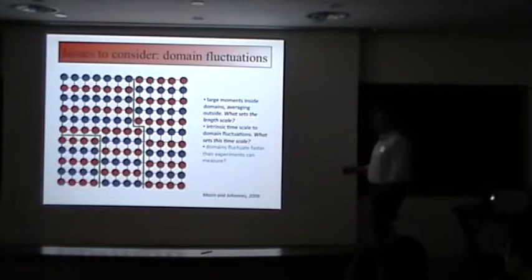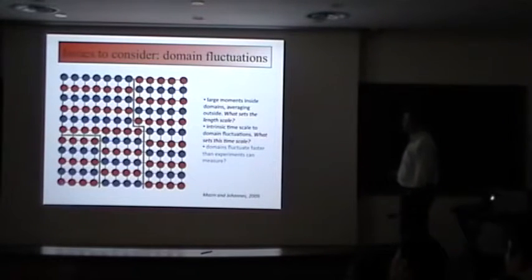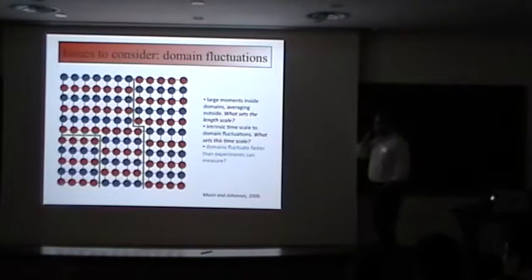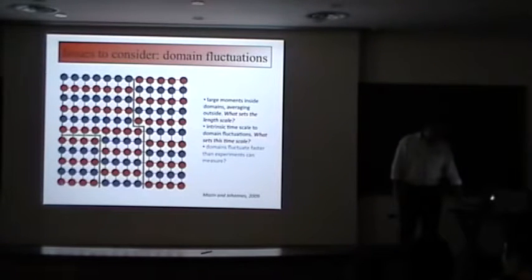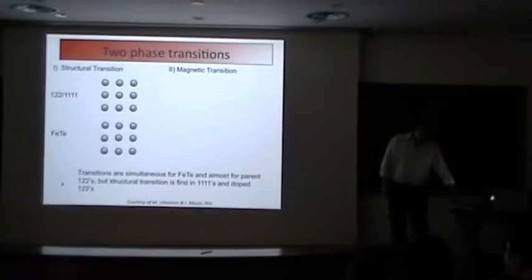So this is a way in which you could reconcile LDA and inhomogeneity of giving smaller moments, but it raises a number of questions: what sets the length scale of these domains, what are the dynamics of the domain walls themselves and how do they fluctuate, is there a time scale connected to it, and have experiments been able to detect this length scale and time scale? If not, are these domains fluctuating faster than experiments would be sensitive to measure this local order? So that's one way of thinking about reconciling it.